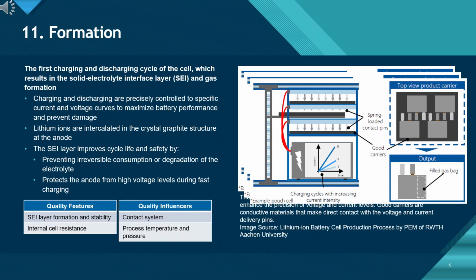Step 11 for formation. This is the first controlled charge-discharge cycle of the cell, and it is one of the most critical steps in determining long-term performance and safety. During this process, lithium ions intercalate into the anode's graphite structure for the first time, and the solid electrolyte interface, SEI, forms. A stable SEI is essential. It prevents continuous electrolyte decomposition, reduces irreversible lithium loss, and protects the anode during high-rate charging.